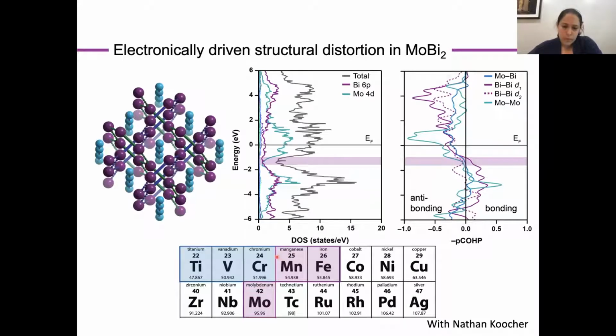And indeed, that helps to explain how by the time we get to the manganese and iron versions of these structures, those phases are both predicted to undergo magnetic phase changes to help to alleviate some of that instability at the Fermi energy. In comparison, by shifting our focus to the 4d transition metal series with molybdenum, in which we would not expect to find such magnetic distortions, I think we've identified something of a limit in accessing this structure type in this phase space, something that I'm excited to continue to explore computationally and experimentally as well.